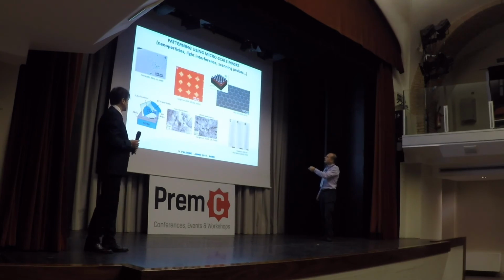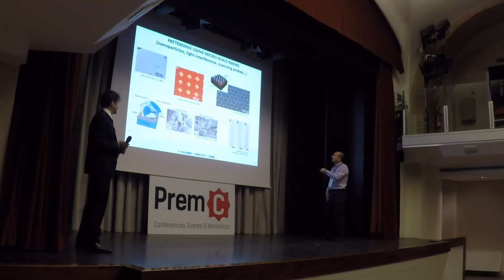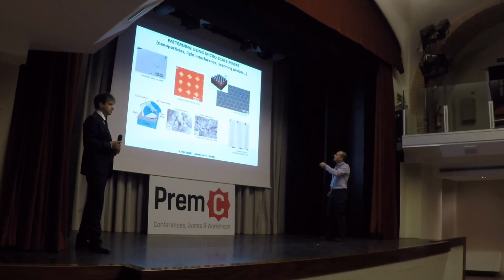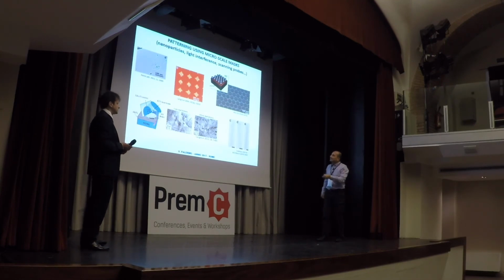But as you can imagine, the edges are not very good. Then they even try to make these kinds of necks. You put spheres on graphene, then you use them as a mask to etch, and you hope to have this kind of thing. They use interference to make these kinds of lines, but it's very difficult to pattern at the nanoscale because to have a finite band gap, you really need a few nanometers with very nice edges.